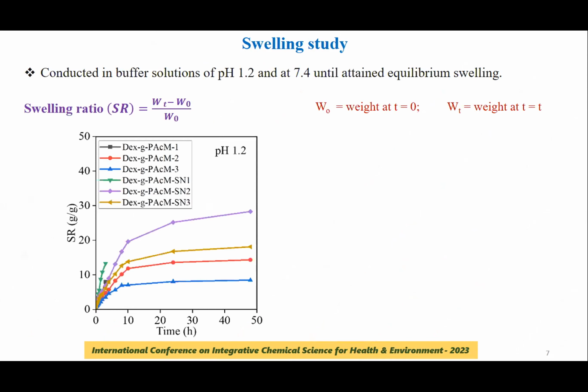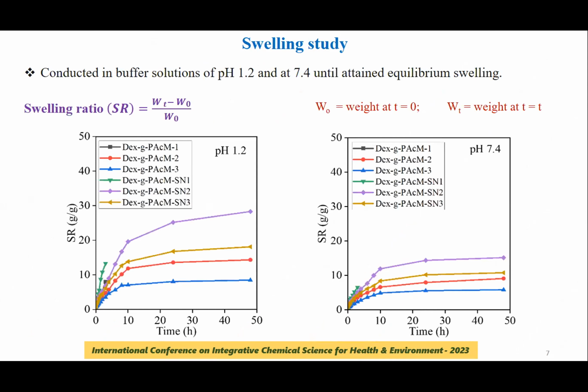At each prescribed time interval, the swelling ratio was calculated. As you can see in these results, there are five observations here. The first observation is that with increased amount of ACM, the swelling ratio decreases. The second observation is that at pH 1.2, materials swell significantly more than at pH 7.4. The third observation is that addition of nanoparticles enhances swelling significantly compared to the parent hydrogel.